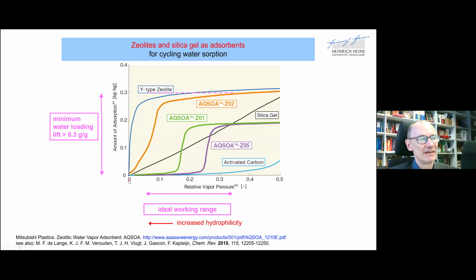And that is not at 0.0 here, where zeolites often have an uptake, but a little bit higher, and but not too high. So it should go from 0.05 to 0.35. This way, it is hydrophilic, but not too hydrophilic, and also not too hydrophobic. So, for example, you see here also active carbon shown, and active carbon is hydrophobic.